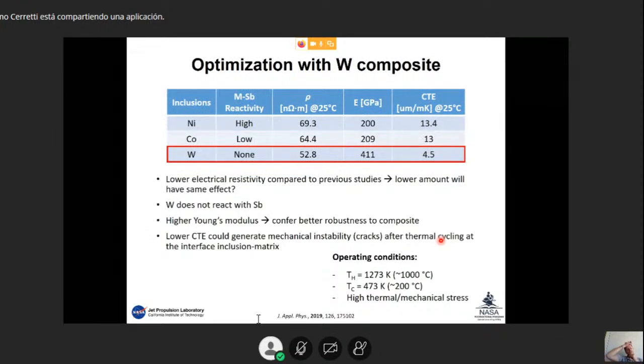After showing the results obtained with cobalt, I thought, okay, what if we use something else? Something different that has a lower electrical resistivity compared to cobalt and a higher Young's modulus. This should allow me to have the same effect, boosting the properties with a smaller amount of inclusions. And that smaller amount of inclusions would probably balance the mismatch in the coefficient of thermal expansion, because tungsten has a very low CTE compared to the one of the matrix material.